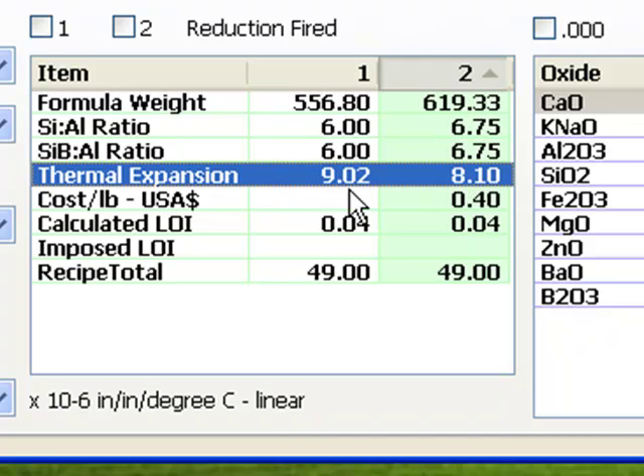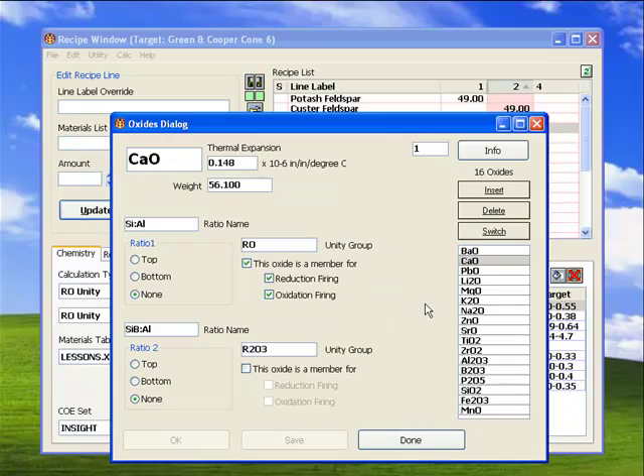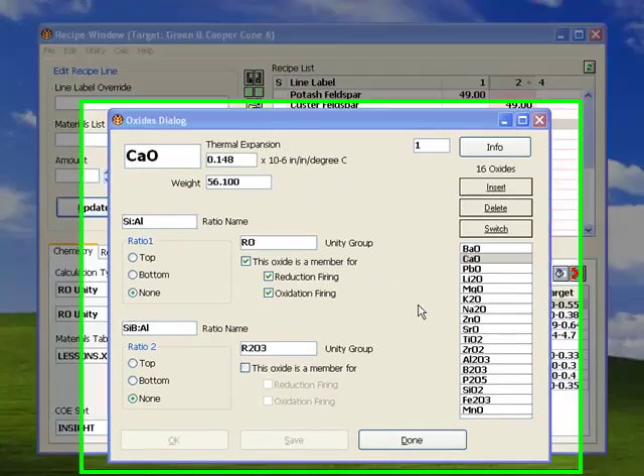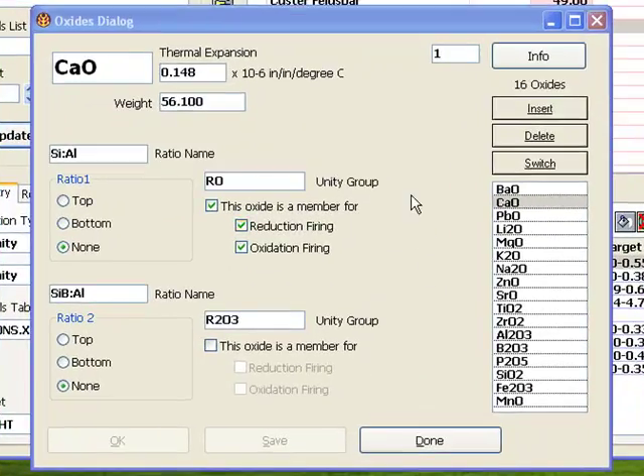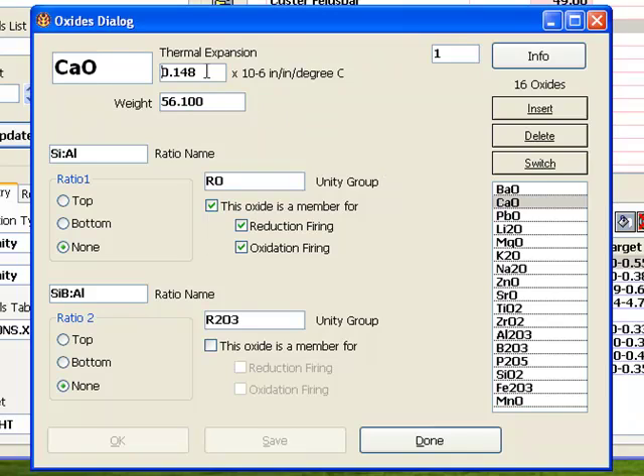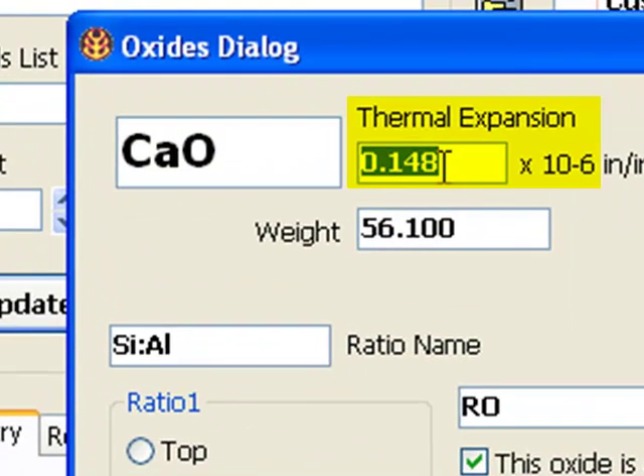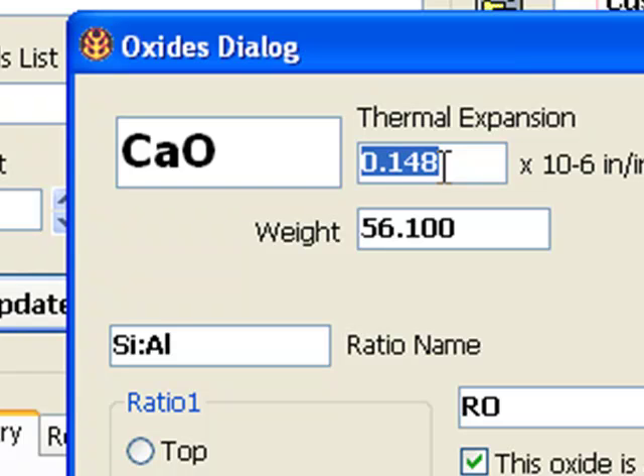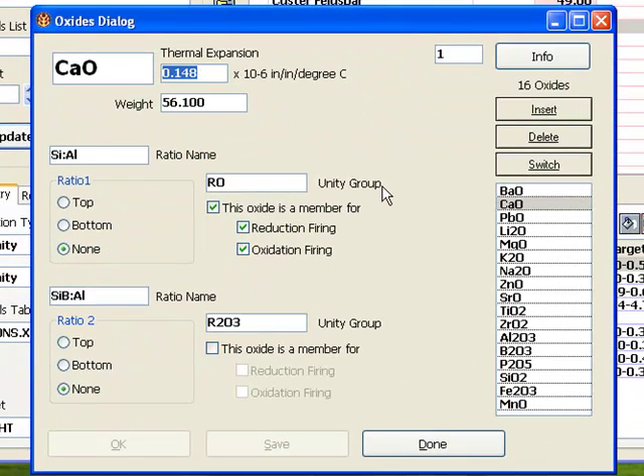Let me show you something else in the Oxides dialog. I'll double-click on the CaO line again. The Oxides dialog appears again. Notice the thermal expansion of CaO. It's 0.148. What does this number mean? Well, you don't really need to worry about it yet. Just consider its relative magnitude. Higher numbers mean crazing. Very low ones mean that a glaze could shiver. Crazing is where the glaze is stretched on the ware and forms a network of cracks. Shivering is where it is compressed onto the ware so much that it flakes off edges to relieve the stress.